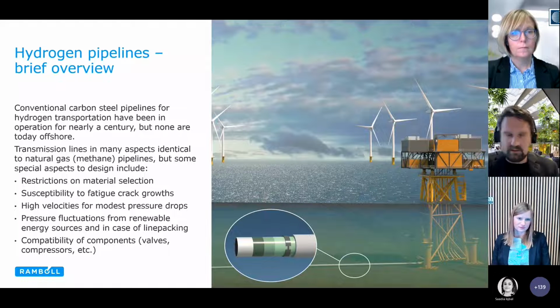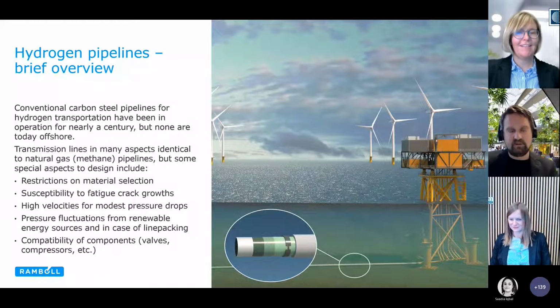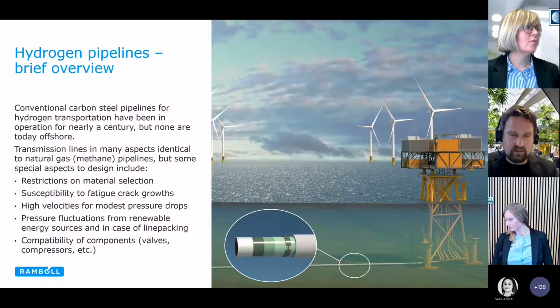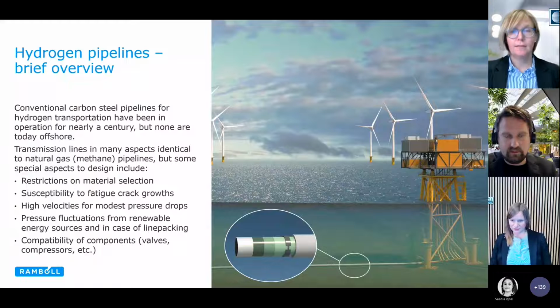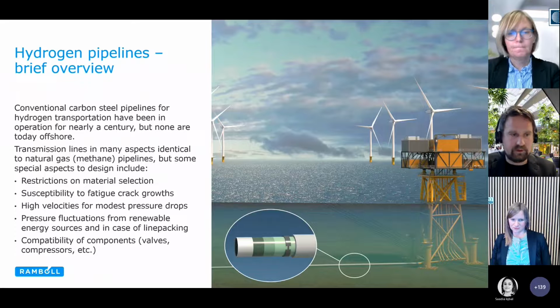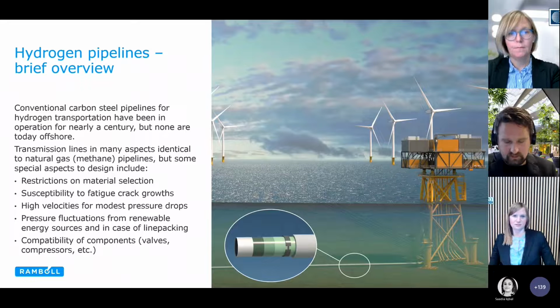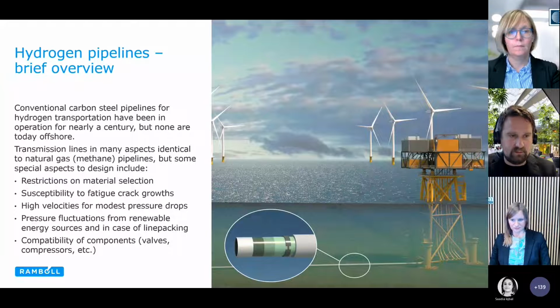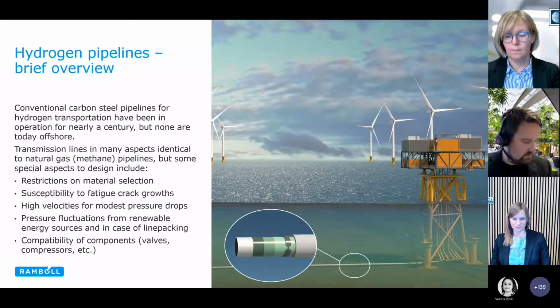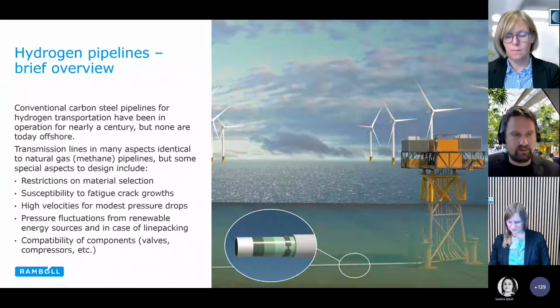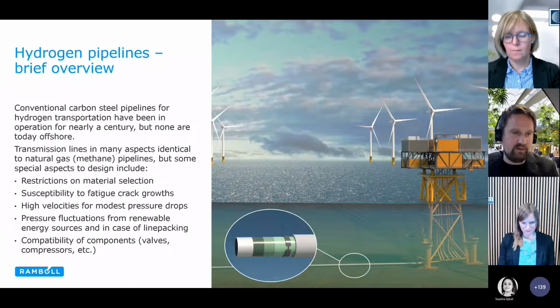There is some discussion on the velocities because due to the lesser energy density of hydrogen compared to natural gas, it seems on the surface of it that the energy transport is only going to be a third of the natural gas. But since it's such a small molecule, it can flow a lot faster. So when we compare flows for identical pressure levels between natural gas and hydrogen, we see the hydrogen compensating for or matching 70-80% of the energy flow of the natural gas. But this in turn turns into very high velocities in the pipeline.